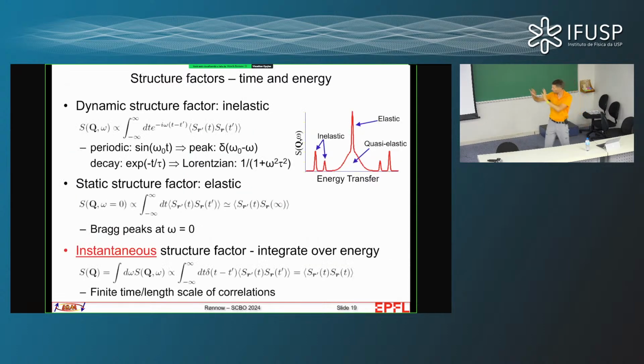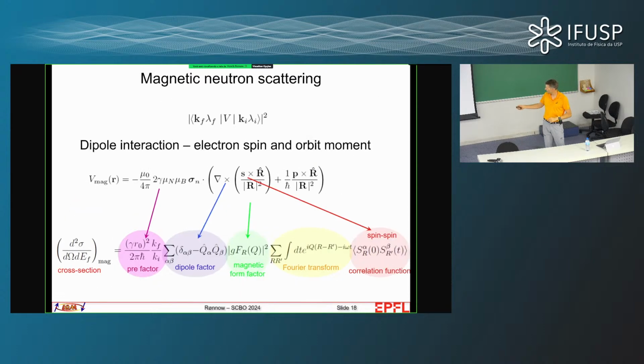Okay, so that's essentially a very, very brief primer to neutron scattering, and the power of neutron scattering is that it is so simple, and that this cross section is always exact. We have many other probes of condensed matter. We can measure resistivity. We can do Raman scattering, X-ray spectroscopy. But very rarely do we know all of the prefactors in the interaction between the sample and the signal that we measure. So neutron scattering is expensive. We need the big machines. It's statistically limited. The interaction is so weak that even when we have big crystals, the statistical quality of our data is limited, but we know very accurately what we're measuring.